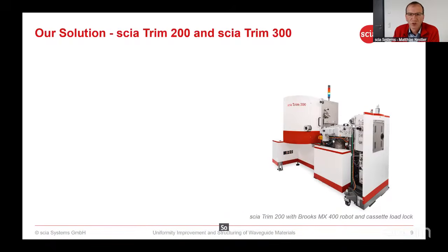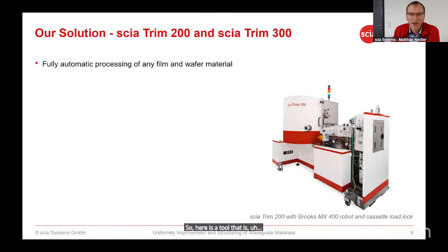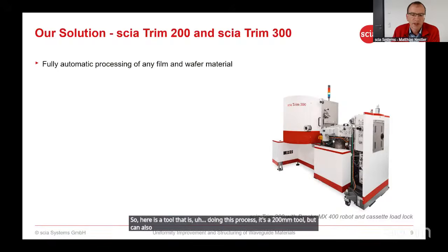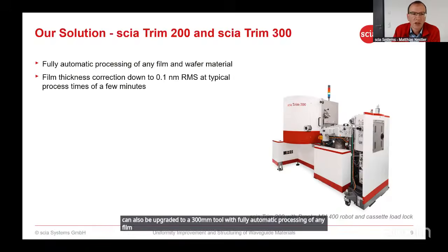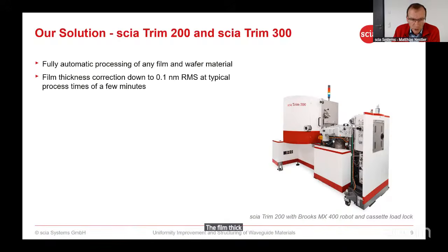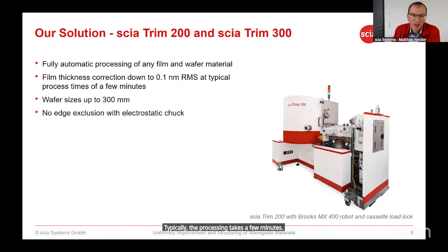So here is a tool that is doing this process. It's a 200 millimeter tool, but can also be upgraded to a 300 millimeter tool with fully automatic processing of any film and wafer material. The film thickness correction could be down to 0.1 nanometer RMS. Typically, the processing takes a few minutes. Wafer size up to 300 millimeter.